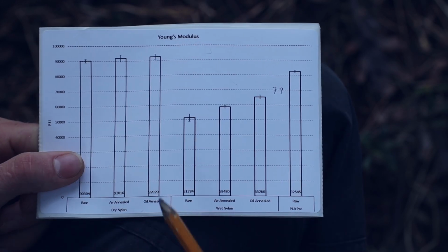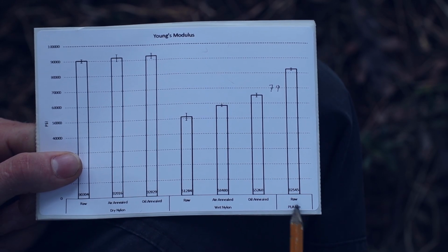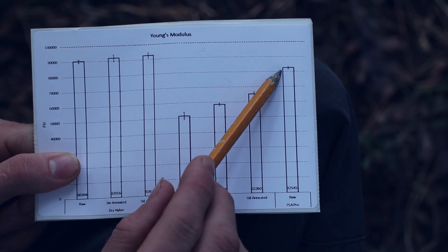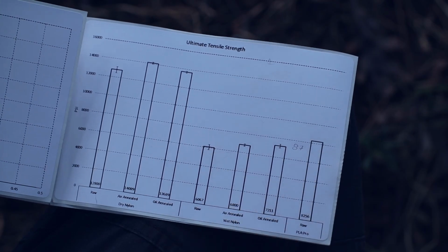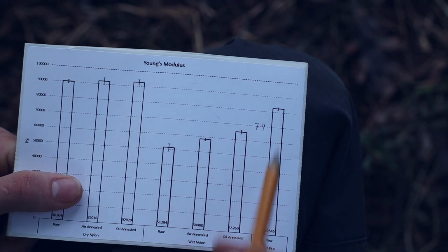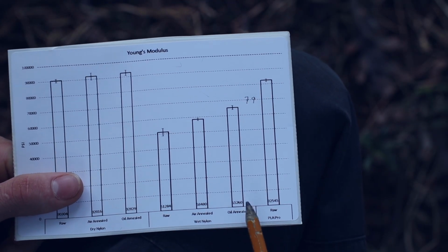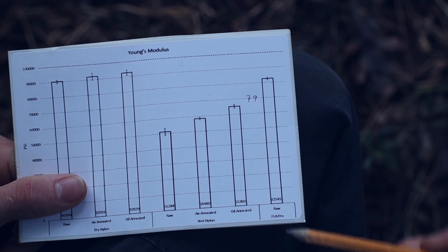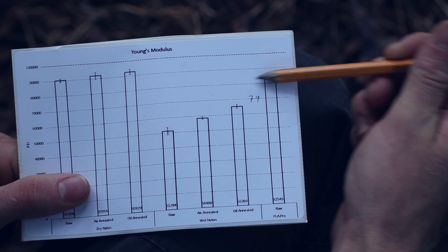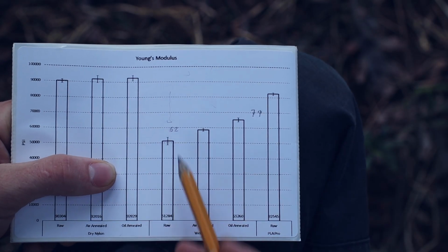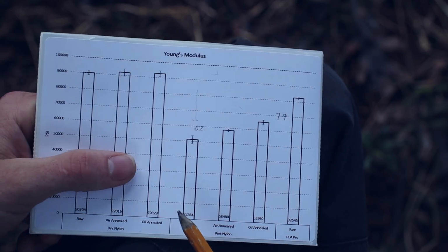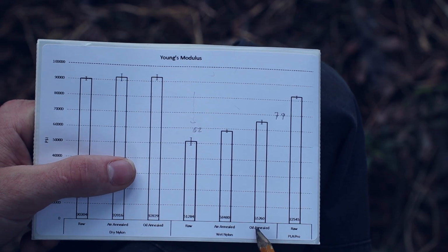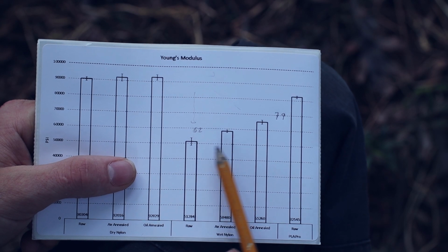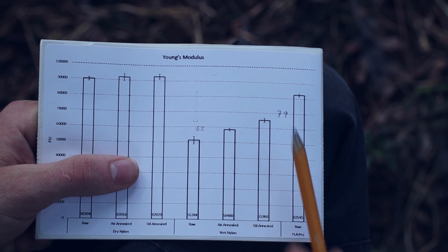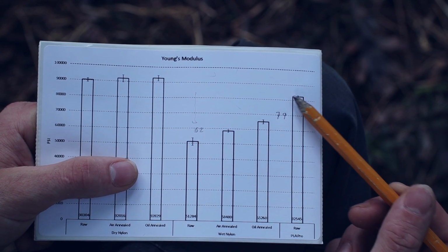And then if we come over here, we can see that the PLA Pro has gotten a lot further ahead and is now, instead of being way down here at like 60% of the strength of the dry nylons, at like 90% of the stiffness. The PLA Pro is actually a very stiff material, and this is kind of the benchmark. That's the stiffness we're going for here. The raw nylon is 62% as stiff as the Polymaker PLA Pro, and the oil annealed is 79%. So that is a significant increase, but still not enough because we really need as much as the Polymaker PLA Pro here.